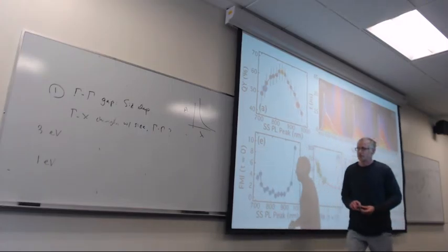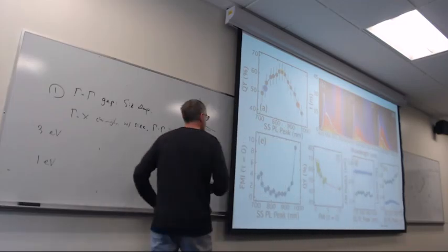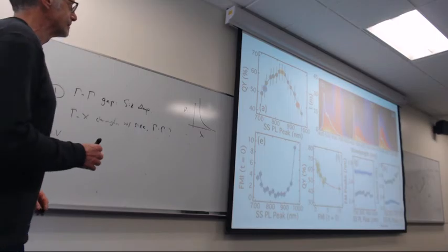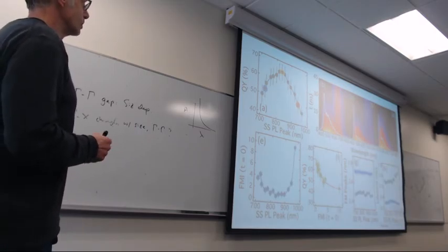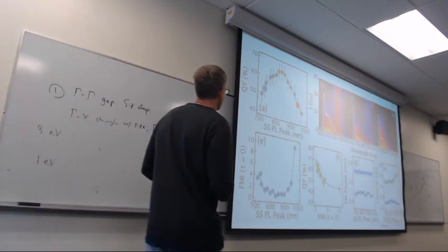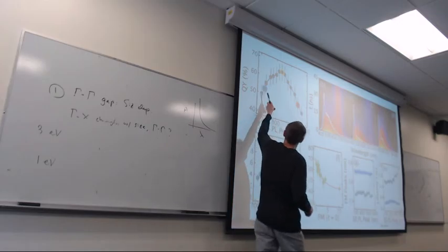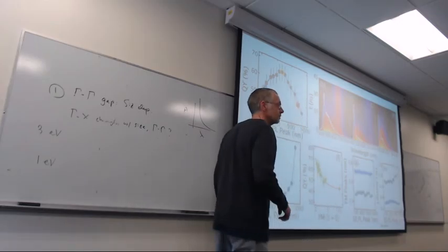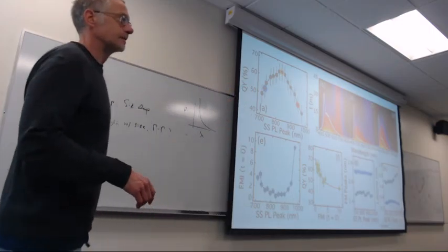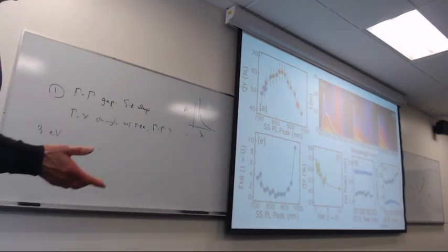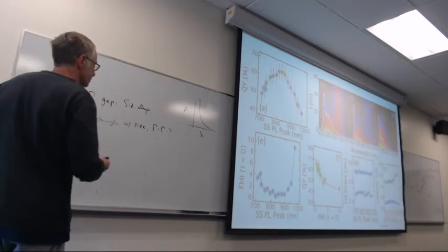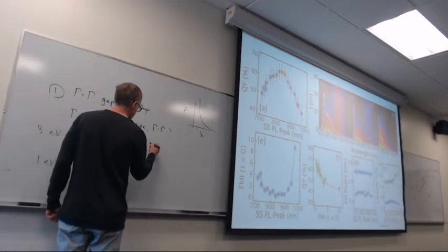My initial intuition was that... But the intensity is changing, right? You're saying the bigger the dot, the slightly higher intensity for this blue shifted peak. No, it's big on either end, and it's low in the middle where the quantum yield is the highest. So it anti-correlates with quantum yield. That's why surface states seem to make sense, except that they should be in the gap, right?